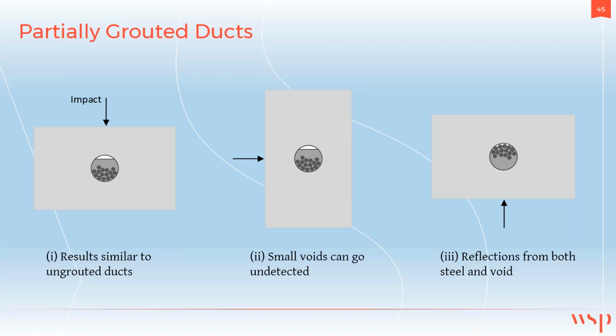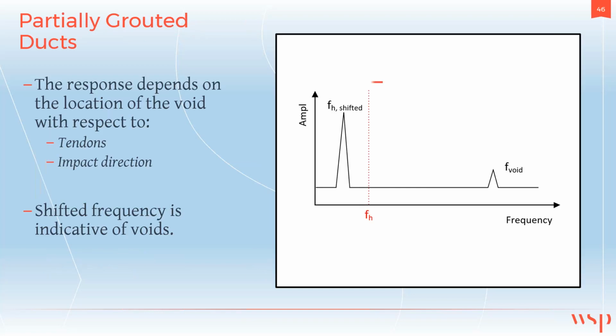Even if this is the case and we have multiple peaks, we can still say that there might be voids because of the shifted frequency. So the shifted frequency is the most important indicator that the duct is probably not fully grouted.